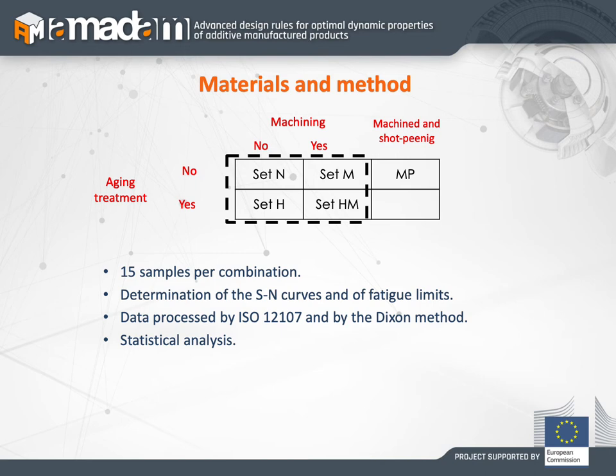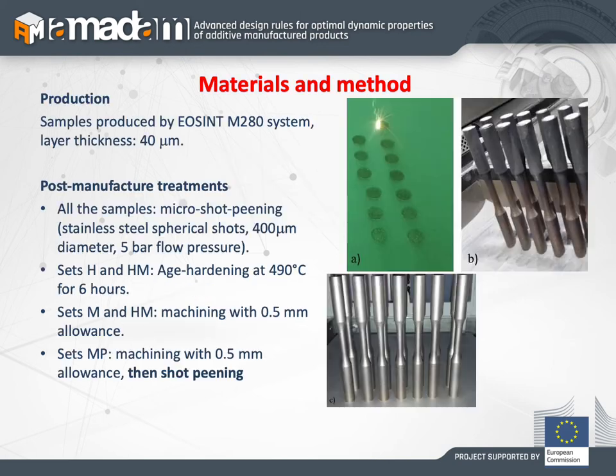There is another cell that is not highlighted here, named MP. That means that after the machining, we also tested some specimens that have the micro shot peening applied after we have machined the specimen, in order to understand if the micro shot peening applied after the machining has an effect on the fatigue results.